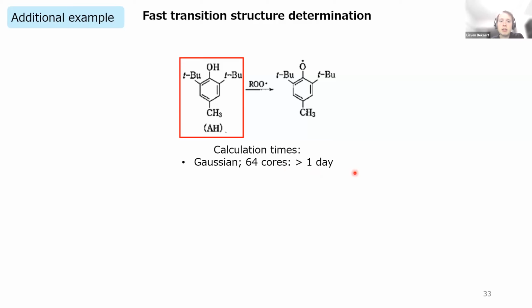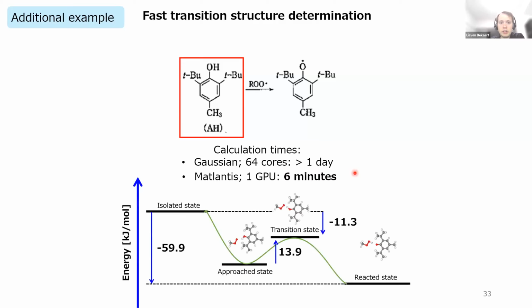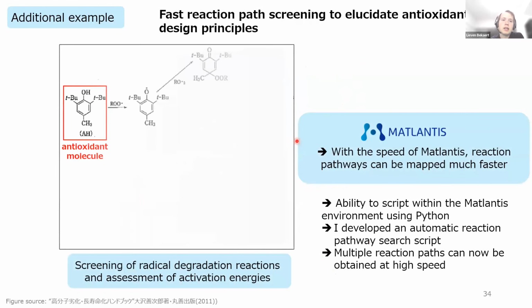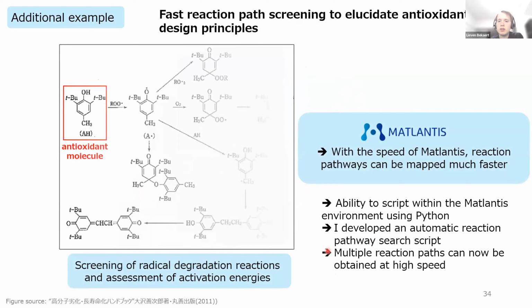Now we performed the same calculation with Matlantis, and with just one GPU, we were able to get it in 6 minutes. So that is a very significant improvement also for these molecular systems. And Matlantis is so fast that, and that was one of the things that I did during those 2 weeks, I developed an automatic reaction pathway search script in which you can automatically map the activation energies for these decomposition reactions.